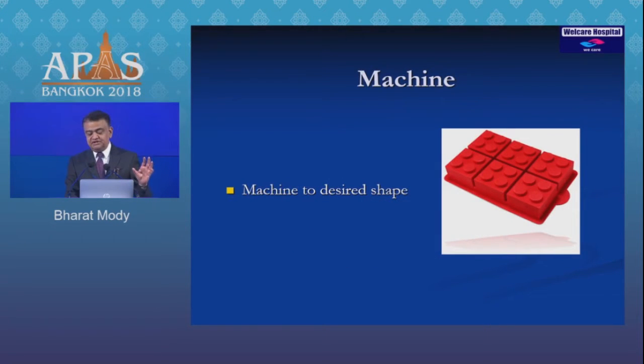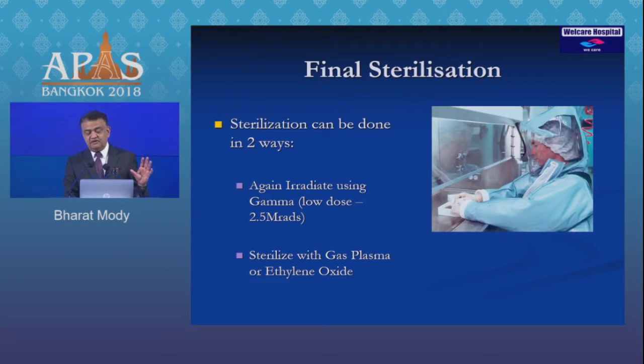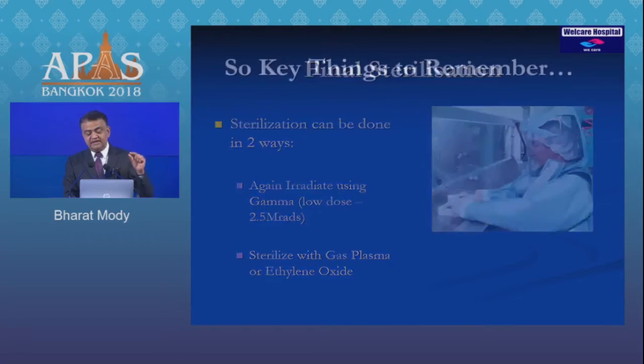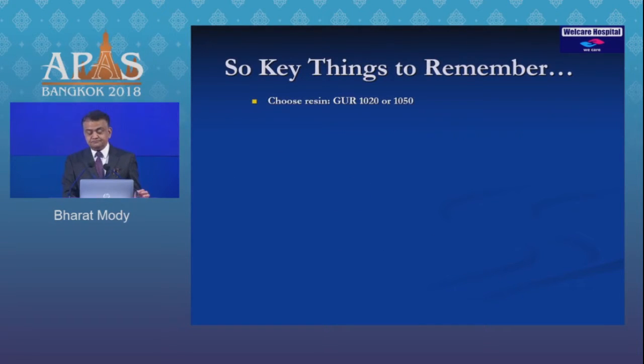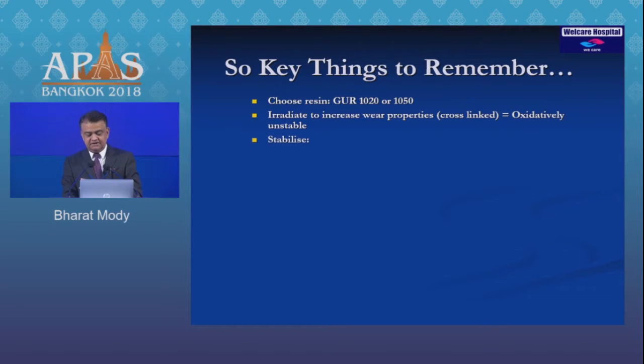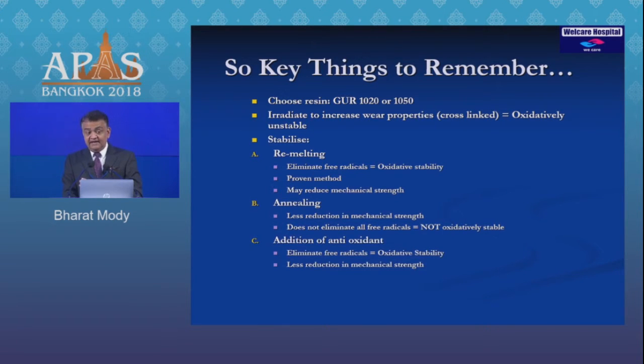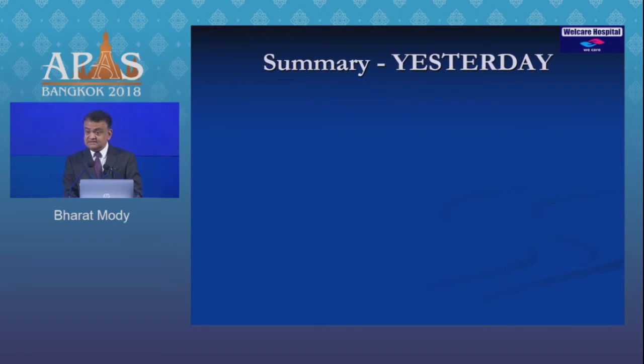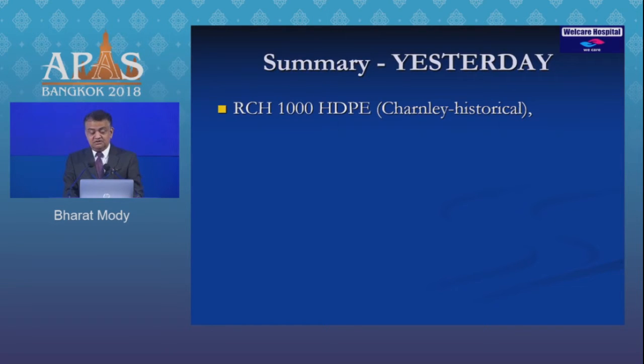Finally, you machine it into the shape that you require and finally sterilize it, and this time with either low dose of gamma radiation or with gas plasma or ETO. So key things to remember: choose the resin 1020 or 1050, irradiate to increase the cross-link. This will cause oxidative instability. So you stabilize it either by remelting or by annealing. You add an antioxidant as an alternative or an additional step to the stabilization process, and finally you machine to shape and sterilize. In summary, yesterday it was historical RCH high density poly which Charnley used.